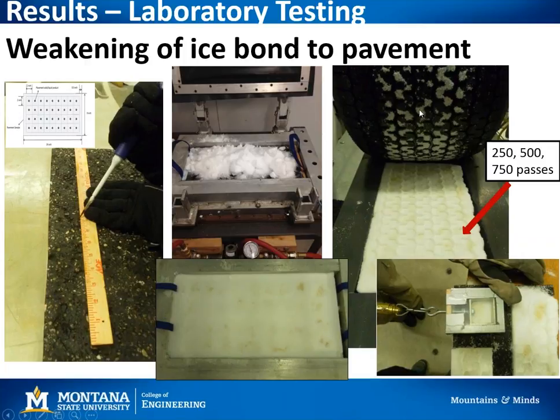And then the pavement sample with the compacted snow was trafficked using this tire, and it was trafficked 250, 500, and 750 passes. And this test method was used to measure the amount of shear strength or shear force that was required to remove this 2-inch by 2-inch section of snow and ice that was bonded to the pavement.